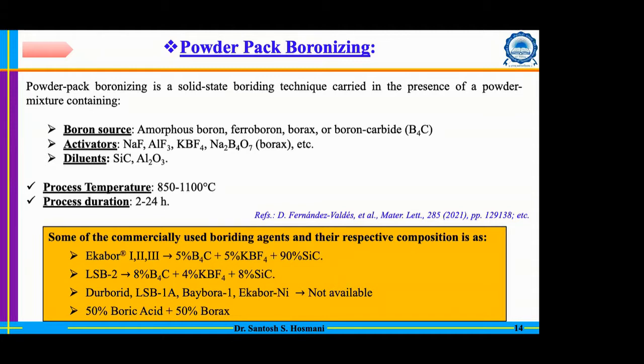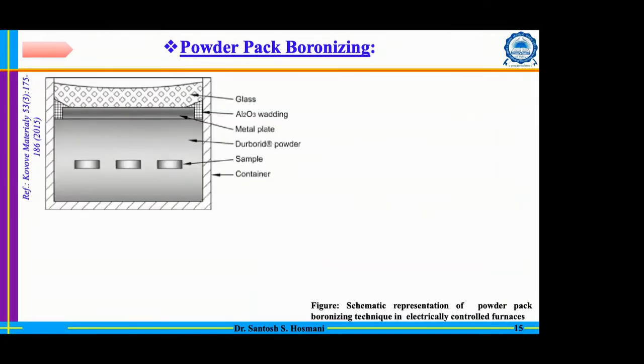And they have not revealed the composition, but it is believed that most of the commercial powders have about 5% of the boron source. You can say B4C, boron carbide, can be there, and 5% of activator will be there, and 90% will be the SiC. Most of the commercial supply, of course, they have not revealed this composition, but it is believed that this is the possible composition these powders must be having. So now the experimental setup.